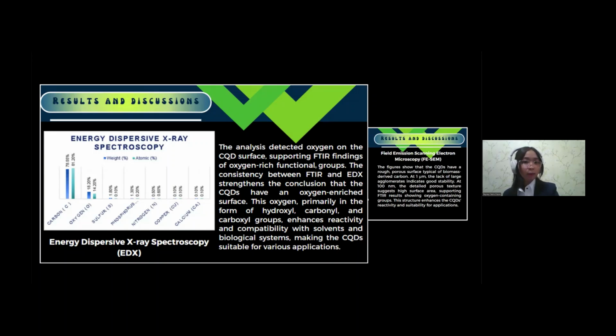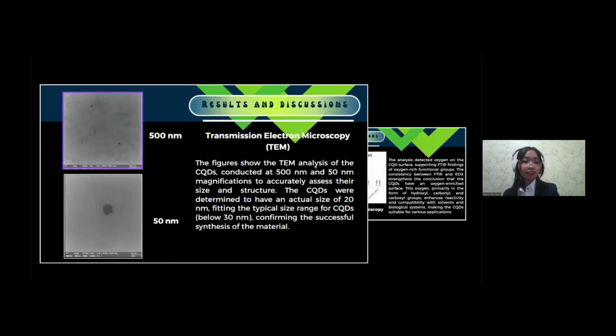Up next is the transmission electron microscopy characterization. These are the figures of the TEM analysis, which was used to measure the size of the CQDs at 500 nanometer and 50 nanometer scales. The CQDs were found to be about 20 nanometers in size, which fits the definition of CQDs as particles smaller than 30 nanometers. This confirms that the synthesis was successful.